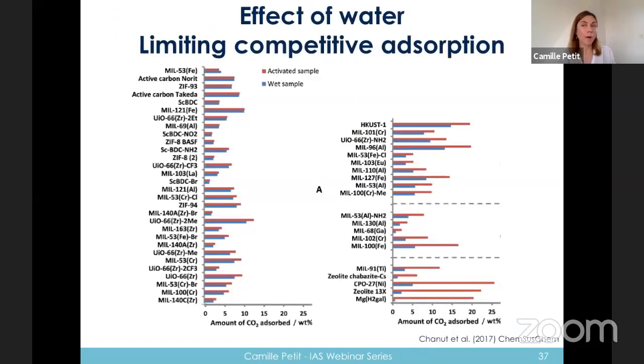Assuming the material is water stable, you now have to consider whether you'll have a competition between water and your desired adsorbate. And here is the example of a study done looking at CO2 uptake in the presence of water. That study considered in a way an extreme scenario, in the sense that the materials were exposed to water first, and then CO2 uptake was measured.